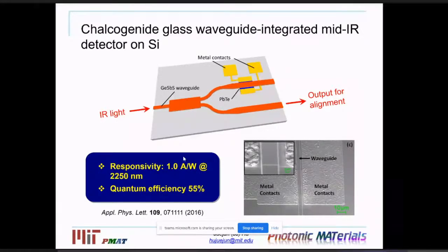What we have measured here, by directly overlaying optical waveguides on top of a lead telluride photodetector, is a high responsivity of about 1 ampere per watt at mid-infrared wavelengths. And this also corresponds to an external quantum efficiency of about 50%.